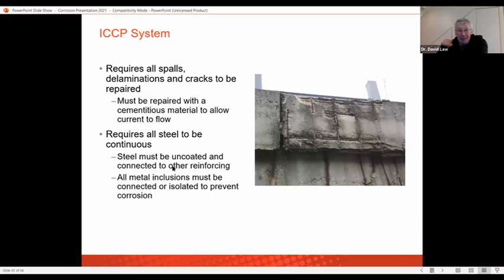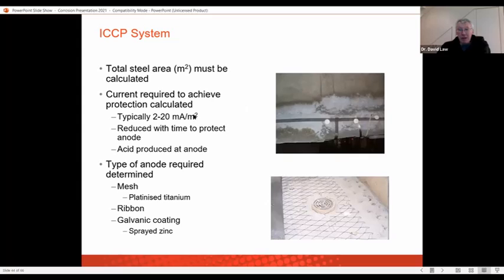And of course, your steel needs to be uncoated. So you can't be looking at this if you've got epoxy coated bars in there. So you work out your total steel area, and then you would typically apply between 2 to 20 milliamps. And when I started this in the late 80s, early 90s, we would rack it up to 20 milliamps and leave it there because we weren't sure it was going to work. And what this did was actually generate quite a lot of acid at these anodes.